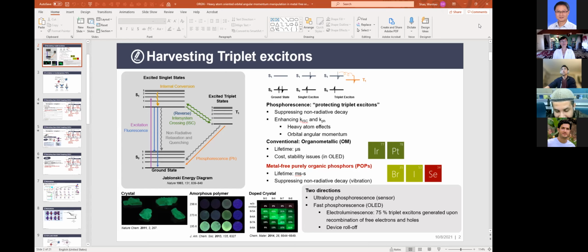What's the commercial application of studying this phosphorescence? That's a very good question. The bigger picture of this material in general, as I mentioned, is that people have studied a lot about sensor applications, where they intentionally made the lifetime of this purely organic phosphor very long. Our interest is more from the fundamental side: how can you make the lifetime faster by engineering the intrinsic spin-orbit coupling? And that's very useful for emitting devices.